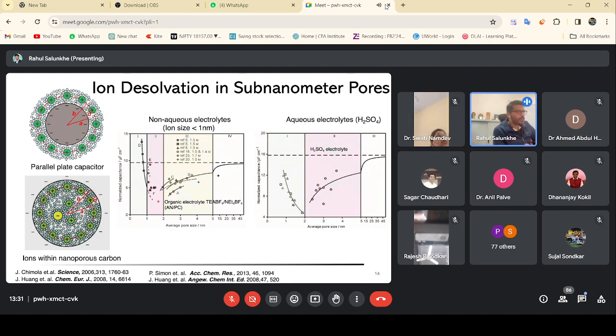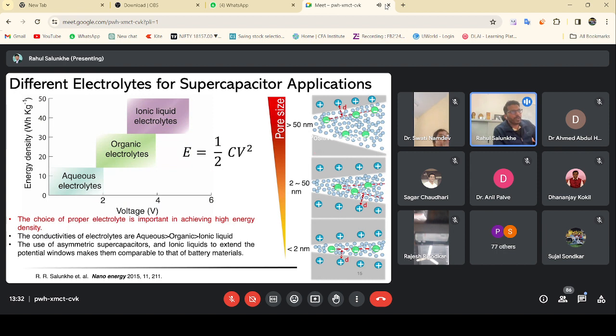On the other hand, if we look at this model, we can see the pores on the surface of the material. This is a typical pore structure, the gray shaded area is our material, and this is positively charged. Now, if the pore size is very large, the ions get adsorbed on the surface of the material, and very near to the surface they can interact effectively with the material, while the interaction is a little bit weak for the ions placed far away.